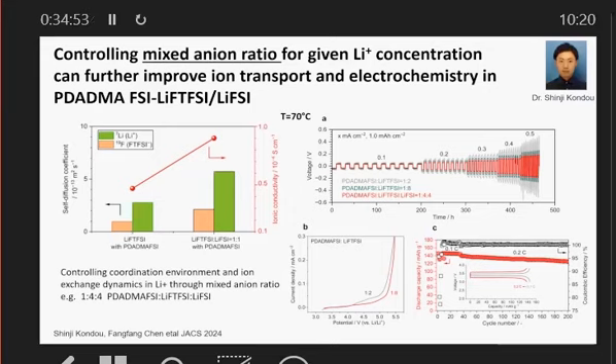So by mixing the anions, we have increased the conductivity on this side. We've also increased the lithium diffusivity by a long way, and again, much higher, while still retaining the high transport number. So this material here, in the range of materials that we tested, is an optimum material.